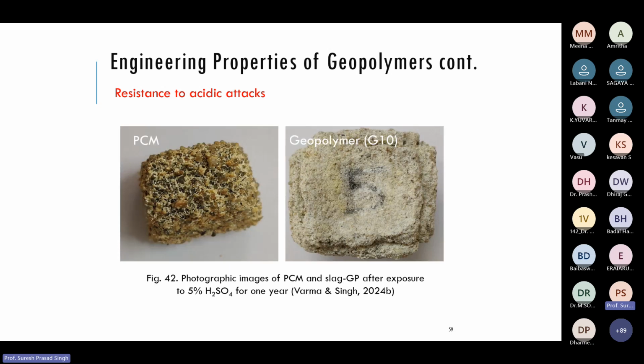You see, these are the samples after the exposure to acid. This is the Portland cement mortar, you see almost all the cementitious material has eaten away. Only these sand particles, quartz particles are there, and lot of voids are there. But here there are still some products, binding materials, which retain the strength. This shows you visually how in an acidic environment there is a reduction of mass as well as strength in ordinary Portland cement mortar and this geopolymer mortar.